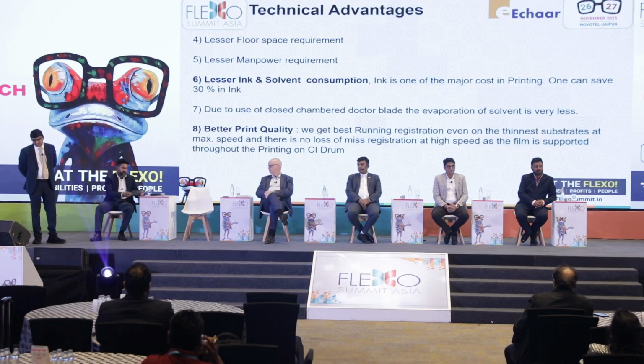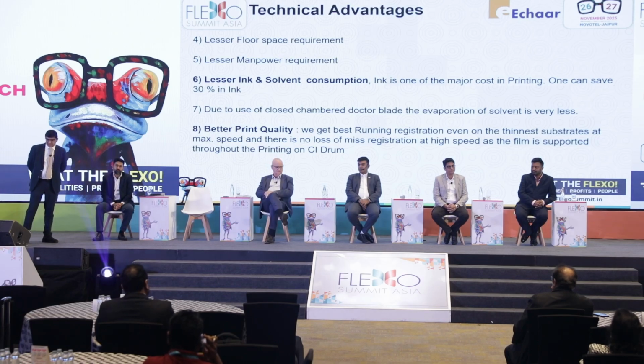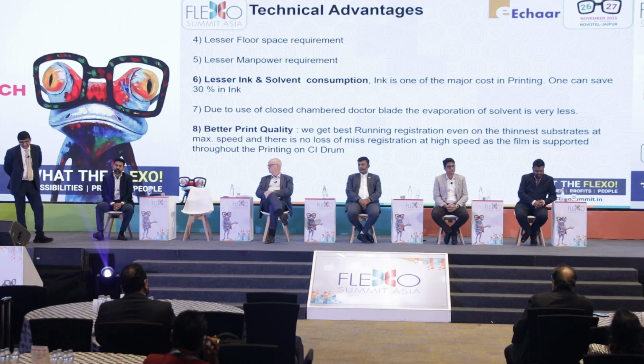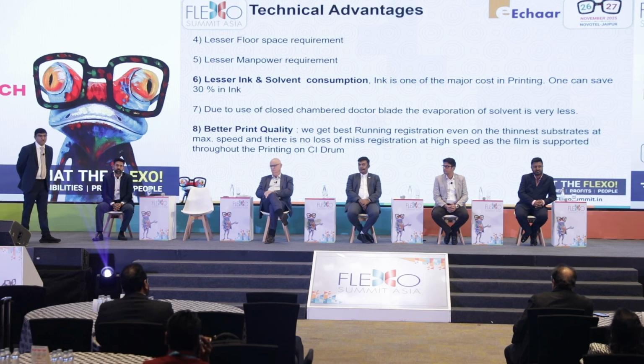Due to the use of a closed chamber doctor blade, the evaporation of solvent is very little. Better print quality: we get the best running registration even on the thinnest substrates. At maximum speed, there is no loss of registration at high speed as the film is supported throughout the printing on the CI drum.